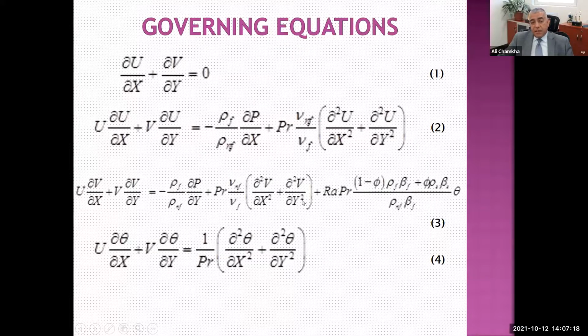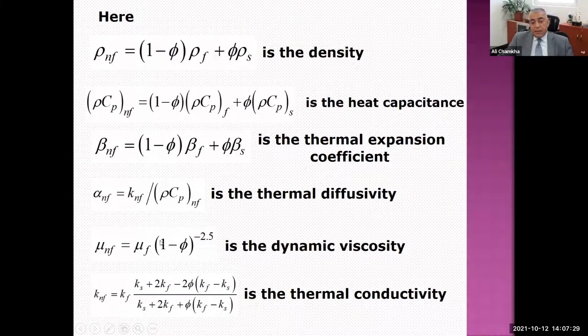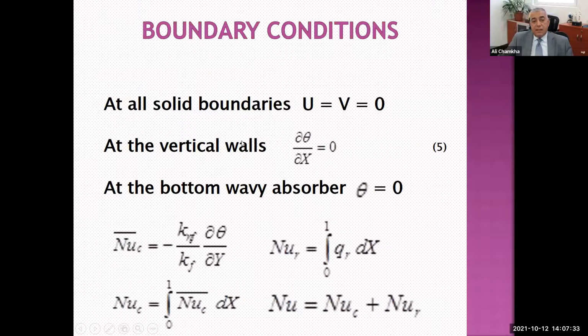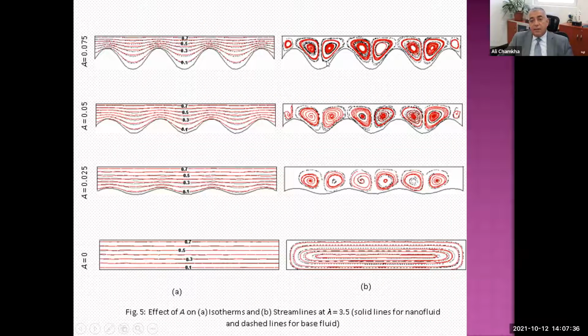Now, we calculated based on the basic principles of Navier-Stokes equations modified to use the nanofluid, as you can see here. And then these are the properties. Here we're using the same thing. This is the Brinkman and Maxwell-Garnett model, no changes here. But if we look at some of the results for different shapes, you will see these are typical isotherms, and these are typical streamlines, and you will see the occurrence of multiple vortices in the system, which will affect the heat transfer. When the absorber has only one shape, no wave, you will see one streamline, one vortex enclosing the whole system.